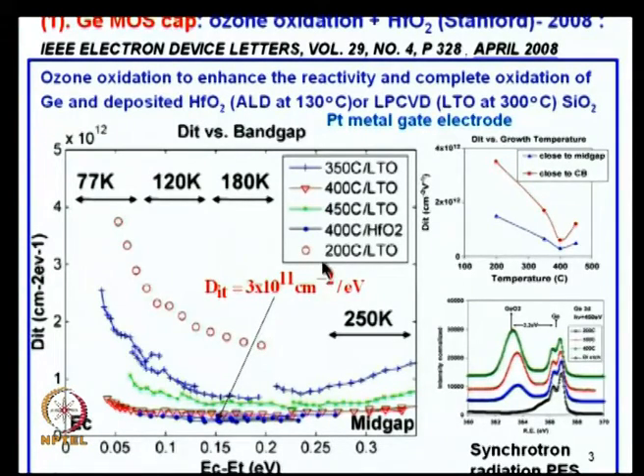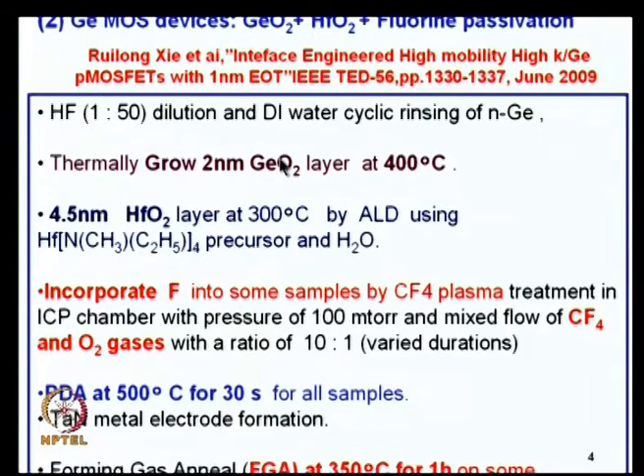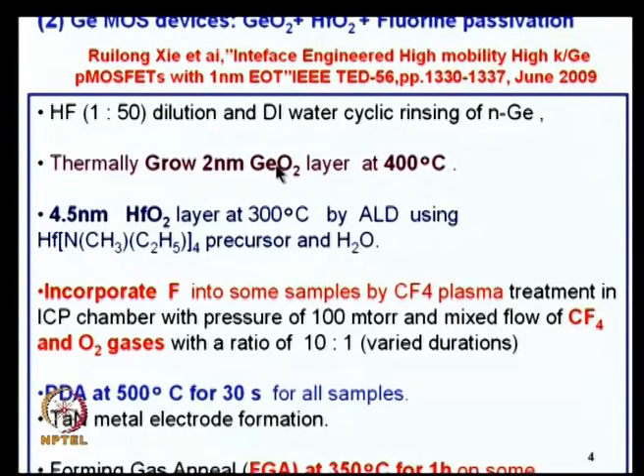The Singapore approach used germanium oxide plus high-k dielectric hafnium oxide. Regular thermal oxidation at 400°C — since GeO2 does not decompose at that temperature — grew 2 nm of germanium oxide. Then atomic layer deposition at 300°C deposited a 4.5 nm hafnium oxide layer on top of the germanium oxide.